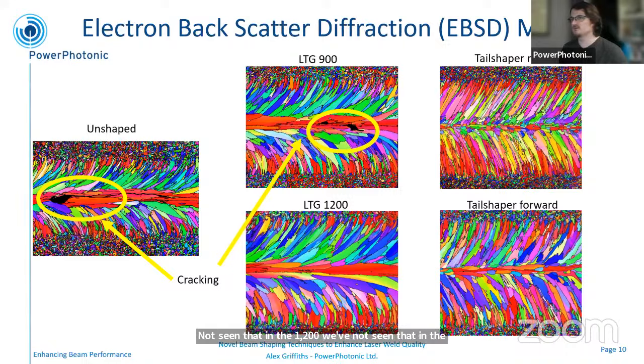We can also see that the grain size and the morphology here is changing quite a lot as you add beam shaping into the equation. So the LTGs improve this, or make the grain structure finer, and then the tail shapers, it's finer still. In particular, the rear tail shaper, we have a lot of small grains along the center line of the weld, which would imply this should be quite a strong weld as well. The tail shaper forward version still has some of this nice small structure. The LTG is a bit less so.